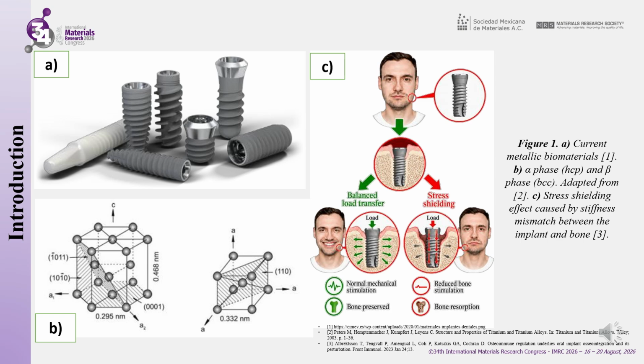Niobium stabilizes the beta phase of titanium, which is body-centered cubic, reducing the elastic modulus and improving mechanical compatibility with bone, whilst hafnium adjusts the thermal and mechanical properties, although its effect on the beta phase is less pronounced. The beta phase provides ductility and fatigue resistance, in contrast to the alpha phase, which is hexagonal close-packed and offers greater mechanical strength. It has been demonstrated that copper modifies the microstructure at low concentrations. It dissolves into the matrix, but at concentrations above 5% by weight, it can induce the formation of titanium-copper intermetallic compounds, thereby increasing hardness and wear resistance, properties that are essential for minimizing particle generation in implants.